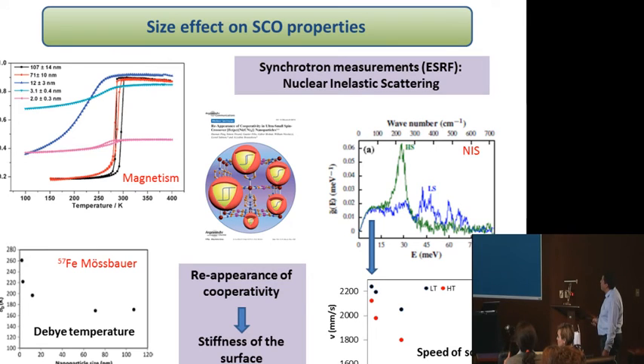So we performed Mössbauer measurements. Using Mössbauer, it's possible to determine the Debye temperature, which is correlated to the stiffness of the particles. And also, we realized synchrotron measurements. Mössbauer synchrotron measurements. From the DOS, it's possible to extract the speed of sound, which also is characteristic of the stiffness of the materials. For both experiments, we have observed that for small nanoparticles, we have an increase of the speed of sound and the Debye temperatures. So these two techniques confirm again that in these small nanoparticles, you have an increase of the rigidity, which can explain the reappearance of the cooperativity in these small nanoparticles.